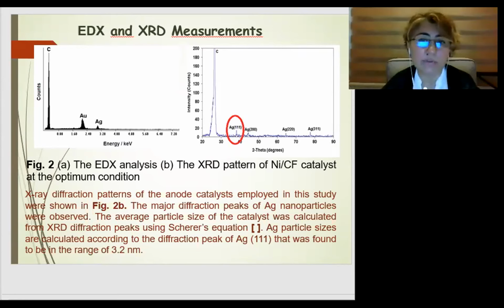X-ray diffraction patterns of the anode catalyst employed in this study are shown in figure 2B, the second one. The major diffraction peaks of the silver nanoparticles were observed, and the Vulcan XC72 showed a typical reflection peak of graphite around 26.34. The peaks at 36, 44, 63, and 77 can be assigned to reflections of the face-centered cubic phase of silver.